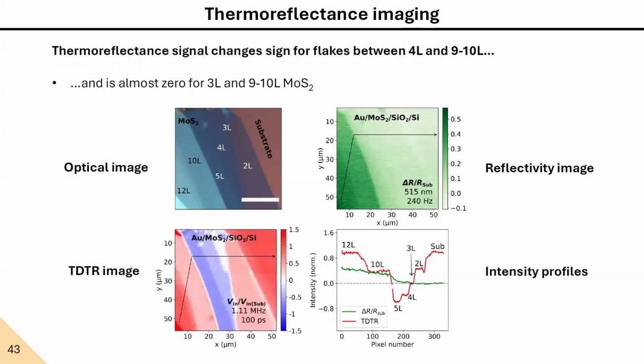If we perform time domain thermoreflectance imaging, first of all, to our surprise, we have single layer resolution. So we can specifically distinguish the different layers in our sample. Second, we see a sign change in the thermoreflectance signal for flakes between 4 and 9 to 10 layer thickness. And third, there are regions that show barely any signal. If we plot the intensity profiles of the reflectivity and of the thermoreflectance along the same line in our sample, we see a monotonous increase in reflectivity and a sign changing, eventually 0 at 3 layers and recovering sign for thicker films.